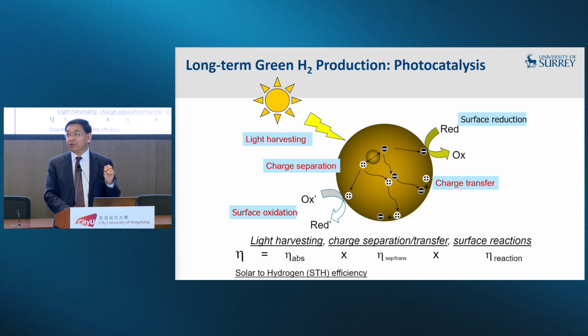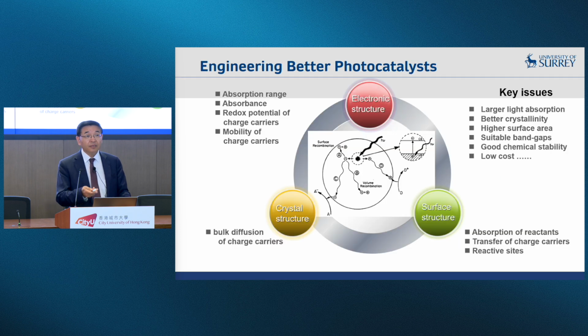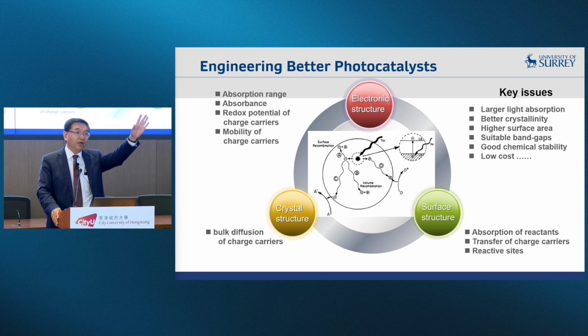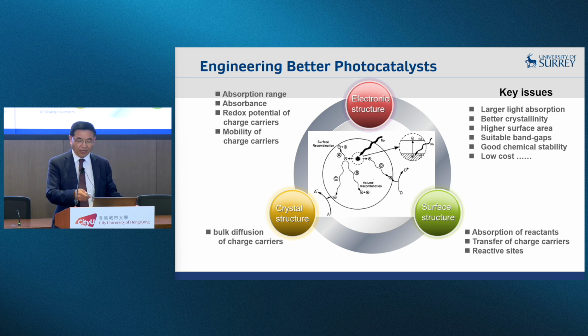The efficiency is actually the product of three components: the light harvesting, which is determined by the electronic structure, the band gap of the semiconductor, and the charge separation and transfer. It's to do with the surface structure as well as the crystal structure, and the surface area and the surface active sites determine the chemical reaction rate. So we have been working on the engineering of photocatalysts for a long time, and we're trying to optimize the electronic structure. On the left-hand side is the absorbance, the redox potential, the carrier mobility, and the crystal structure in terms of the bulk diffusion, and surface structure in terms of the reactants and the reactive sites.